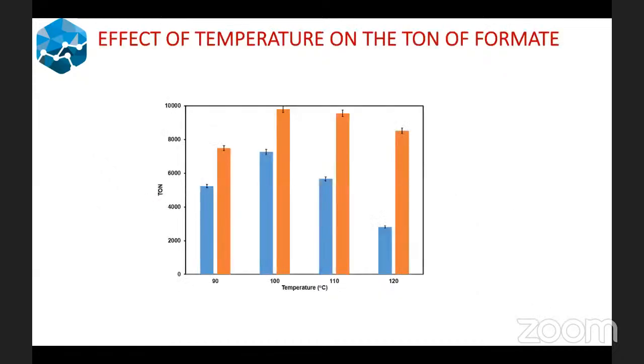Okay. And then we looked at the effects of temperature on the yield of formate that is produced in both cases. The blue represents the magnesium-based MOF, and your orange represents the manganese-based MOF. As you can see, as we increase temperature for the manganese-based MOF, the optimum temperature is at 100 degrees, that is close to 9,800 something. And of course, the turnover number decreases due to decomposition of the formate around 120.